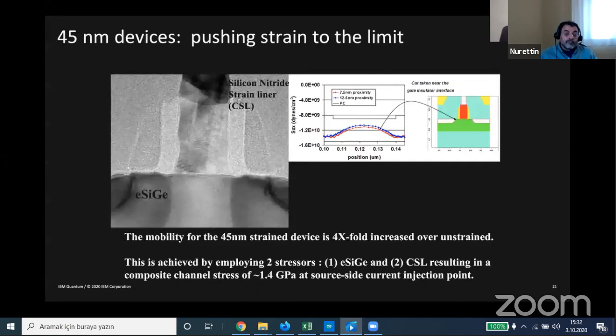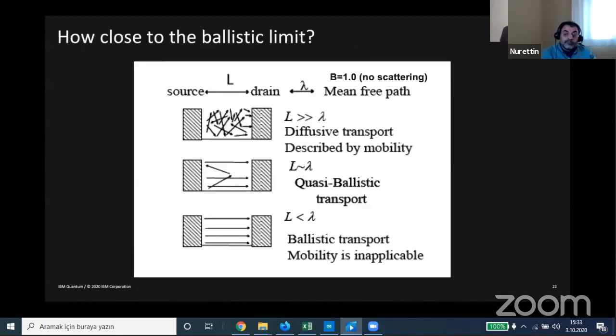To do that at the 45 nanometer node, we combined very high close proximity embedded silicon germanium with compressive stress liner to achieve a mobility over unstrained silicon of 4x. And these two stressors, when combined, boosted the stress at the source side current injection point to a level of around 1.4 gigapascals. So we said pushing strain to the limit. The question then was scaling down to the future was how close are we to the ballistic limit?